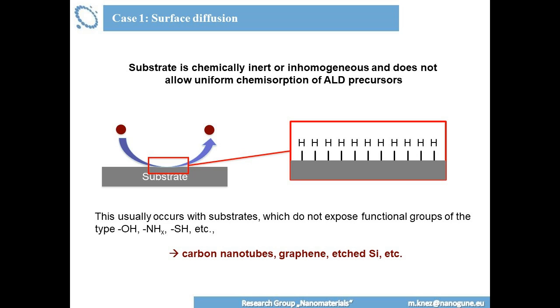Normally you would say it will bounce away. The precursor will come from the gas phase to the substrate. There is no functional group, so it will desorb again. Of course, that's the ideal case. In an ideal case, if you completely inertize a substrate, you will not have a coating. But how many cases are ideal? So that's the next question.